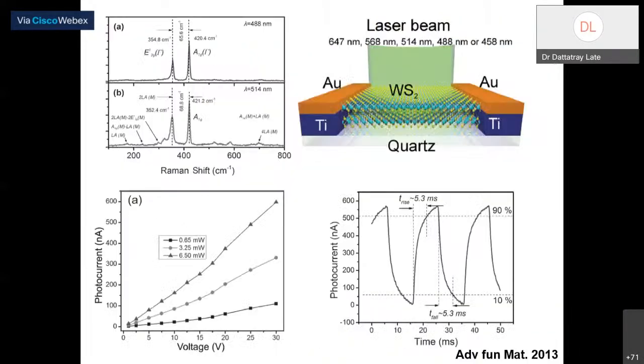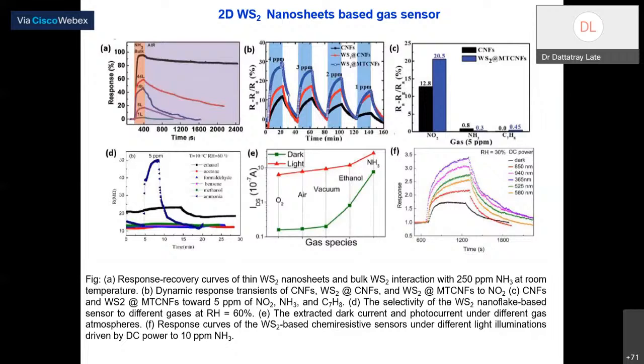Again, this is prepared by the CVD method. I have characterized it using XRD, Raman, and all these things. Here you can see the response and recovery time is almost 5.3 milliseconds, just in milliseconds. Still, I have some options to improve it, but this is enough to have application in these kinds of devices, right? So here I have done experiments for two-dimensional WS2.